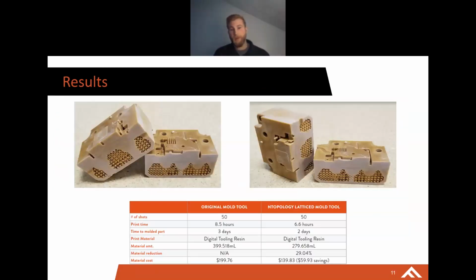So here's some of the results from this. This is a 50-shot mold test. So we only run to 50 shots. We don't run to failure. So we didn't see any failures with this mold on the original or on the lattice mold. What we did see, however, is a significant reduction in resin and in time.